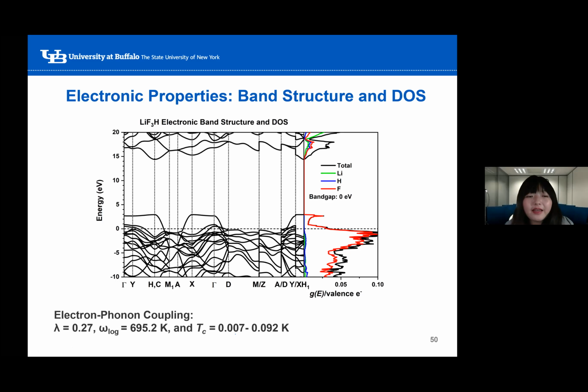Because it's metallic, we decided to estimate its Tc value and calculate the electron-phonon coupling parameters, and it's a really bad superconductor. Actually, we cannot call it a superconductor. So the conclusion would be that the low-lying ternary lithium fluoride hydrogen systems are not good candidates for superconductivity.